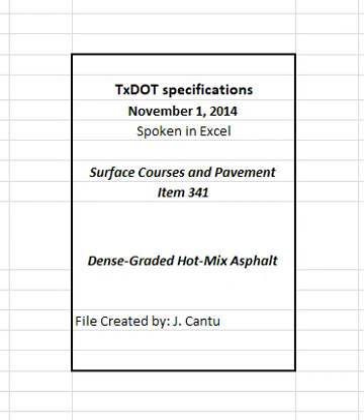Furnish CSS1H, SS1H, or a PG binder with a minimum high temperature grade of PG58 for tack coat binder in accordance with Item 300, Asphalts, Oils, and Emulsions. Specialized or preferred tack coat materials may be allowed or required when shown on the plans. Do not dilute emulsified asphalts at the terminal, in the field, or at any other location before use.